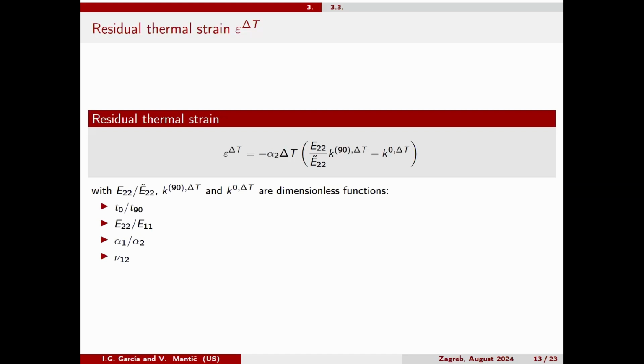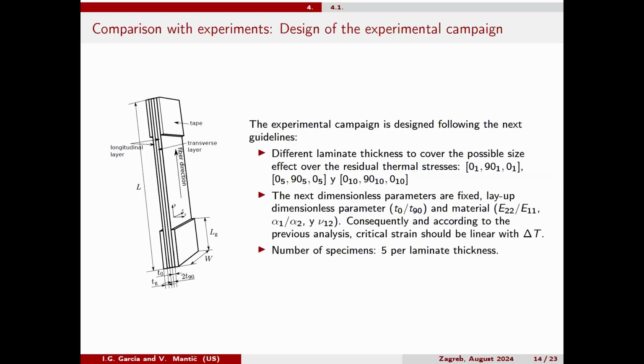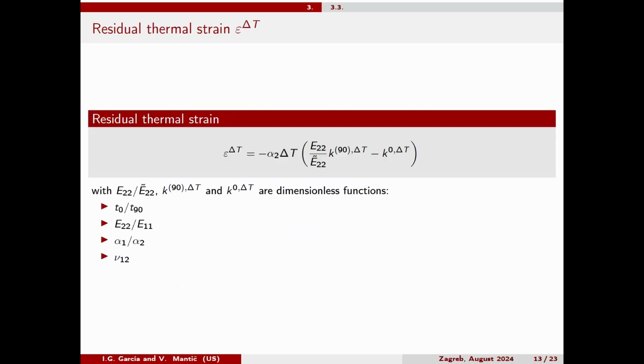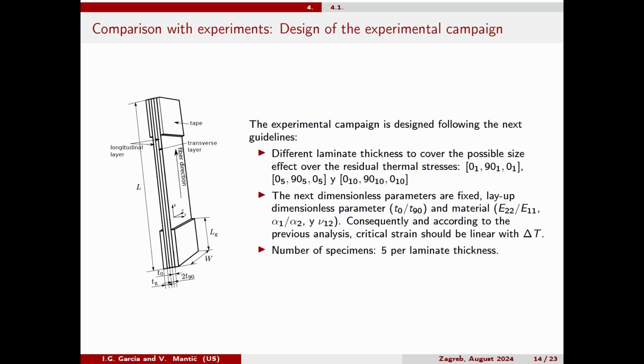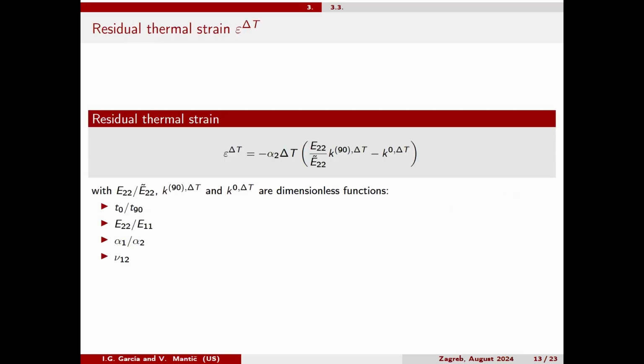So we designed some experimental campaign for evaluating if this strategy is accurate or not for the prediction. We did some classical plain specimens that are classical for this kind of composite. With the next strategies, we fix the ratio of the outer to the inner ply thickness in order to fix this parameter here, and we fix, of course, the material. So all the parameters here are fixed.